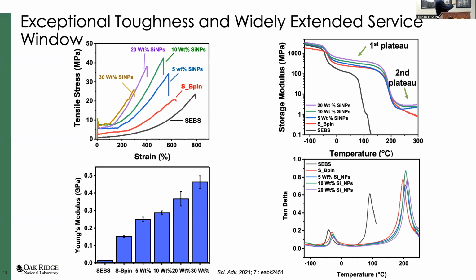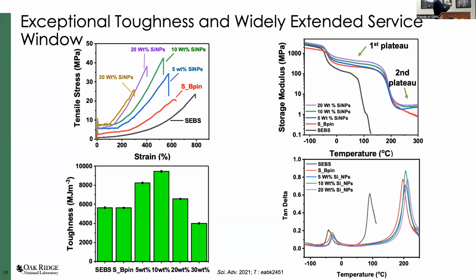Another thing we noticed is from the DMA curve, this temperature. It's showing here the useful temperature range. Starting materials like this range. This is a useful range because once you go to higher temperature, it's kind of slow. So what's showing here between this and this is about an extension of 100 C of useful range. So that's one thing that happened. But then, this is also toughness on this one, and this is a little better, stronger material.